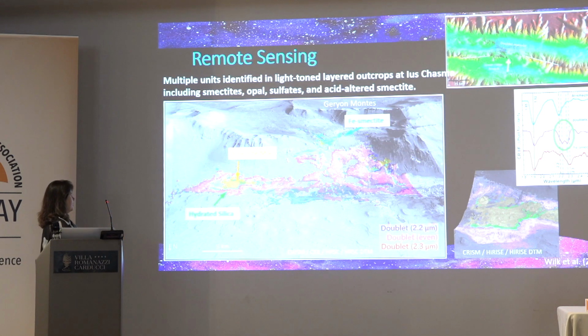And then there are some smectites here that got altered, and I used some work that Jana Madejová did a while ago with acid-treated smectites to inform what we think is happening here. And I saw she's here, and I'm hoping to talk to her about that a little bit. But we see this doublet in the spectra that's not like the aluminum smectites or the iron smectites, and so we think it's acid-treated smectite.